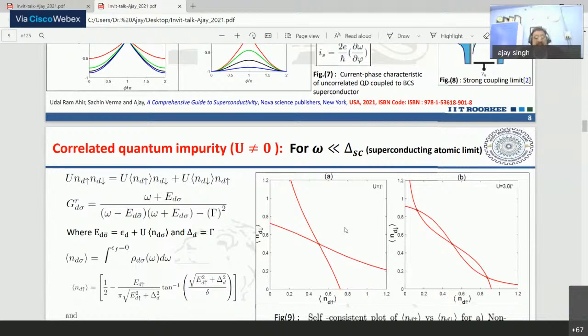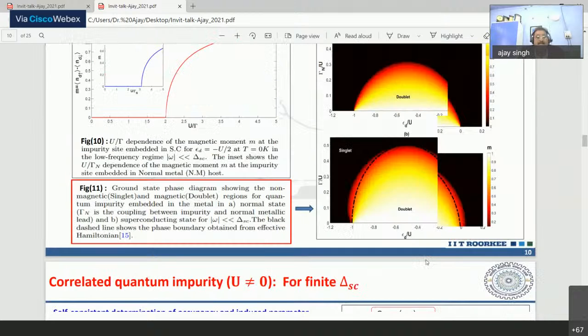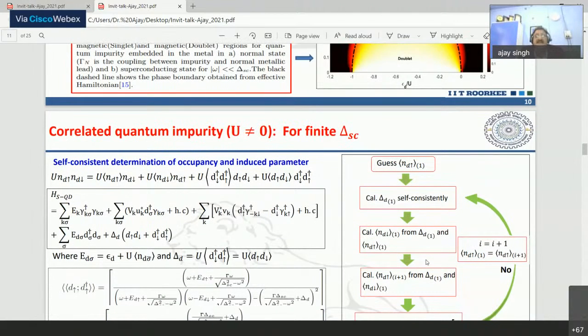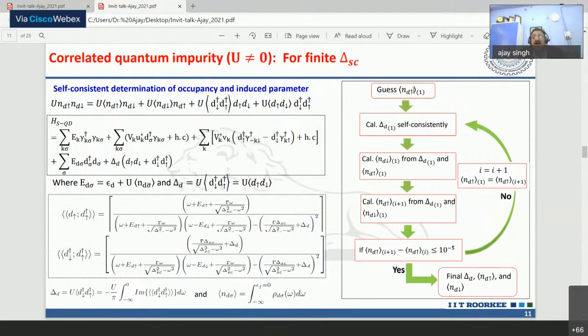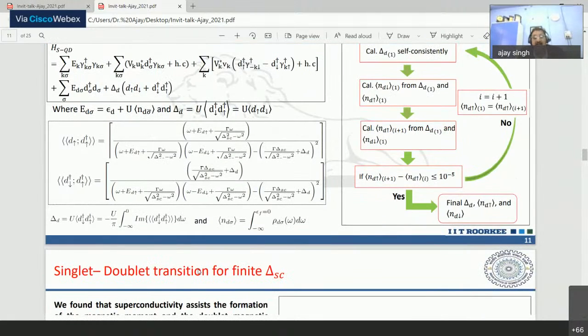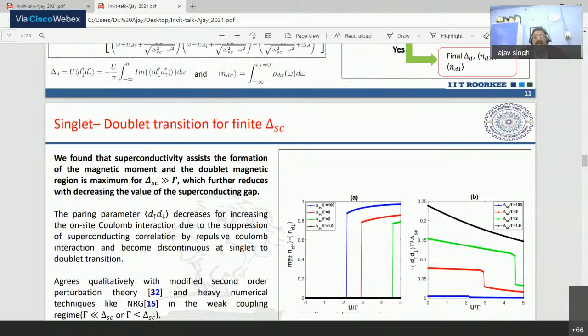In a superconducting system, for omega less than the superconducting order parameter, there is a robust doublet phase which is probable, and the singlet phase shows a suppression. And this shows that in a particular regime, the magnetic moment on the dot becomes robust because it supports a doublet transition. Besides this, we have also extended this result for finite delta, and a heavy numerical computation was done on MATLAB by taking the self-consistency loop, and these calculations are extended, and we then plotted the magnetization or difference of the magnetic moment as a function of Coulomb energy.